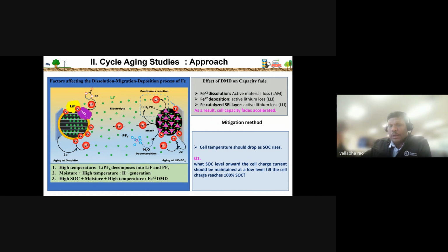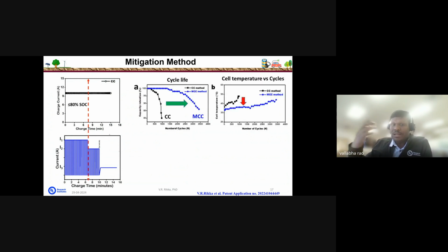So how can we reduce the cell temperature rise over the cycles? For this we have defined different test protocols. If we look here, up to the end of the charge in constant current mode, the current will be the same and higher. For example, if you are charging at the 4C rate, it will be almost 10 amperes for a 2.58 ampere-hour cell. So we designed the protocol in such a way that we reduce the current at the end of the cell voltage, to see whether it can reduce the cell temperature. That showed significant changes in the cell temperature rise over the cycles, and the cycle life increased almost 3 to 4 times compared with the conventional